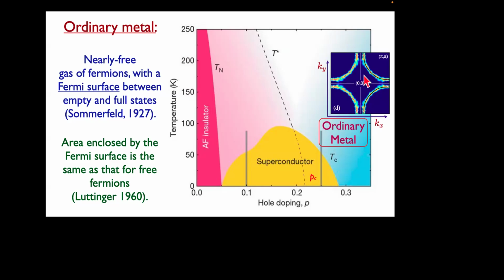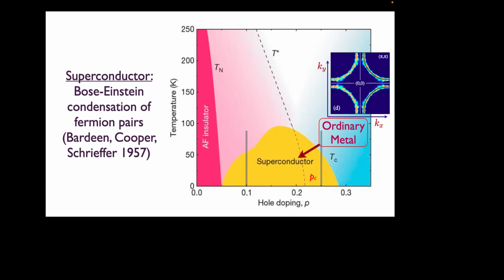Then you can ask, well, what about the superconductivity? Well, we do have a theory of superconductivity due to Bardeen, Cooper and Schrieffer in '57, which said that you start with one of these Sommerfeld metals, and then you put in some weak attraction between the electrons near the Fermi surface, and that will give you a superconductor. Now, in the ordinary superconductors, the old superconductors, that attraction is due to phonons. But here there were already suggestions, even before the discovery of these materials, that the antiferromagnetic spin fluctuations could induce superconductivity via an attraction on the Fermi surface in a higher angular momentum channel. And that also, it seems, worked out in the end, although quantitatively not accurate. You could start from this kind of metal and really get the right type of superconductivity, the so-called D-wave superconductivity that's actually observed. So that's a very strong success for theory.